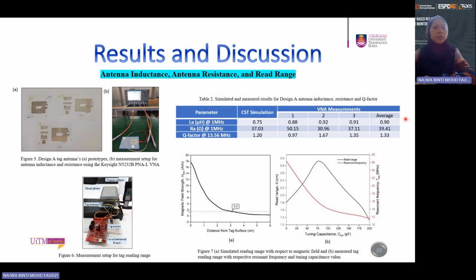So now we go through the results and discussion parts. This is the three samples of printed design A antenna by using hybrid graphene-based conductive material. The first measurement that has been conducted is to measure the inductance and the resistance of the antenna by using a vector analyzer here, and the result has been compared with the simulated value.